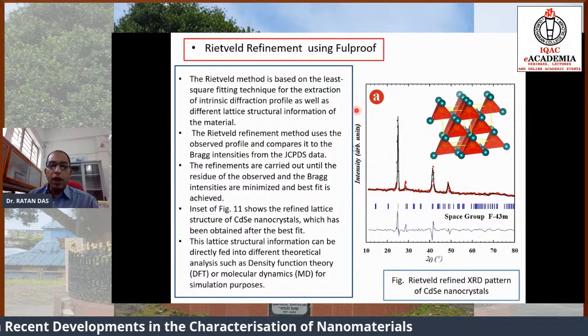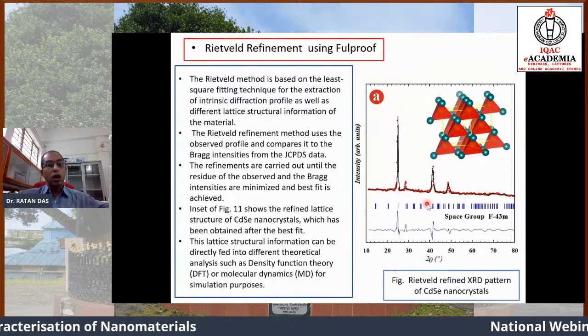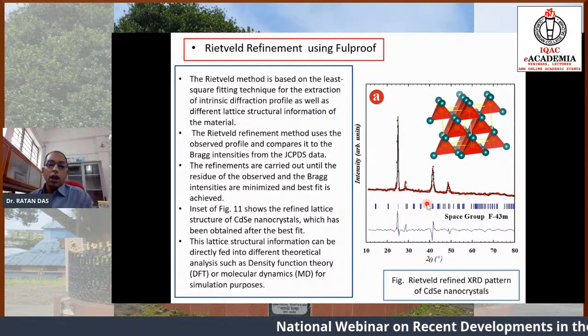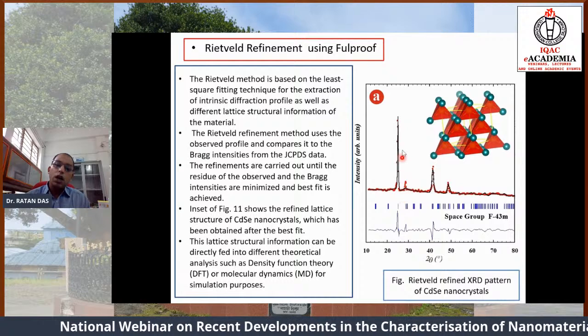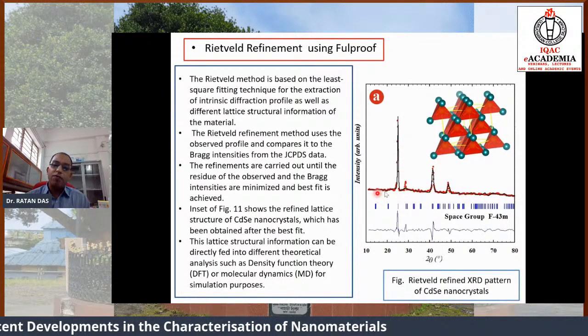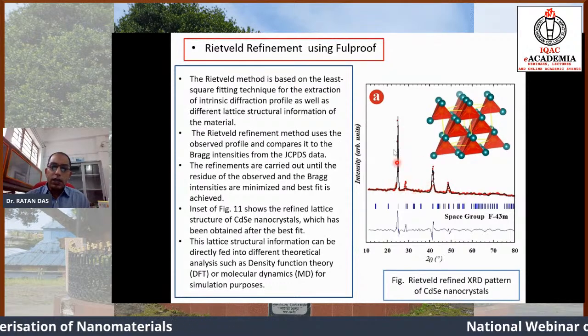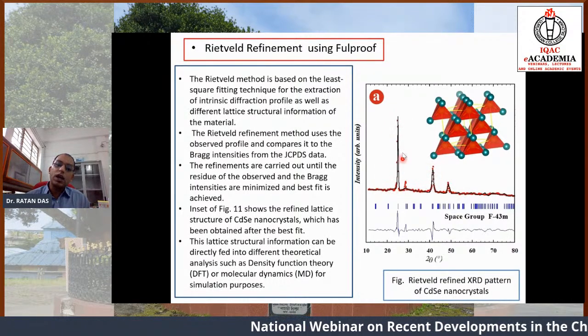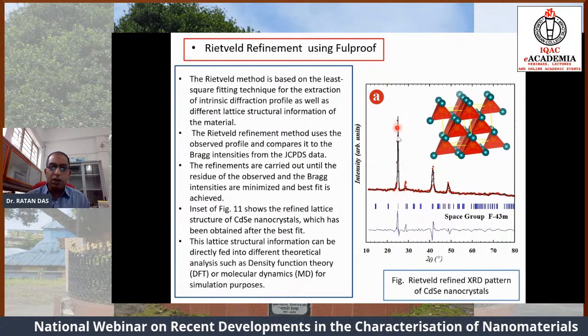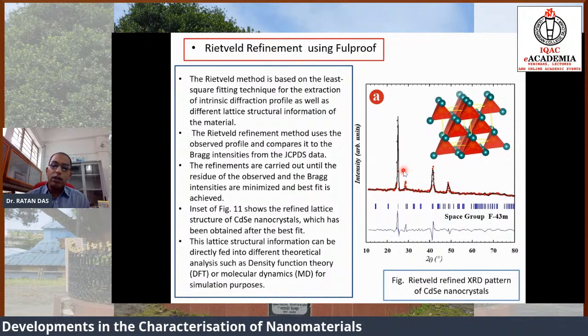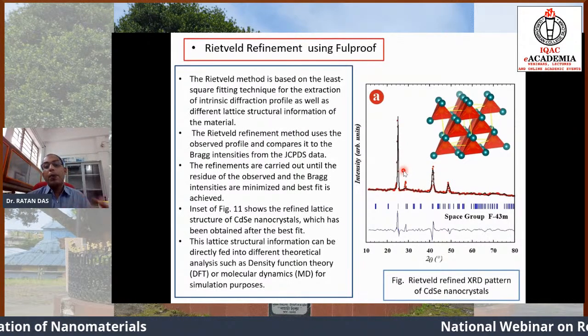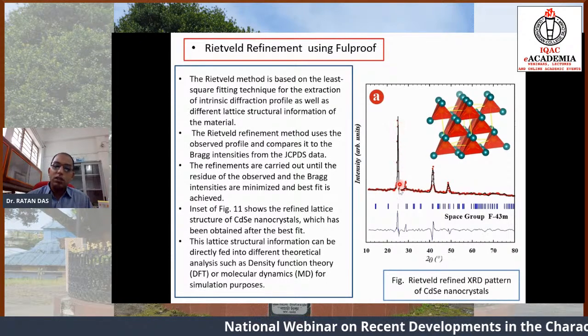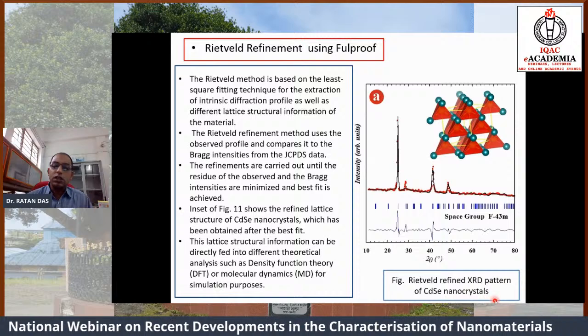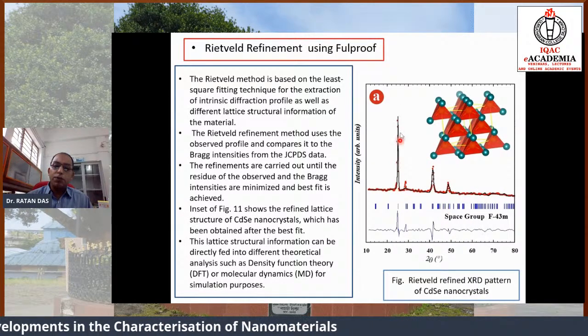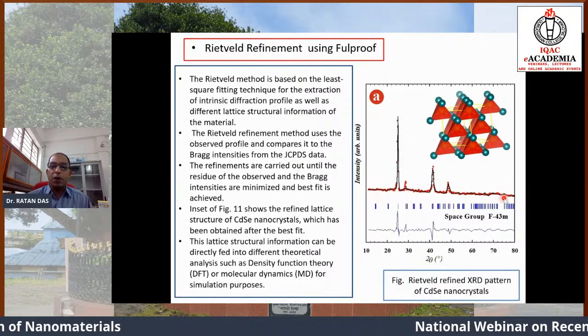Considering a known diffraction pattern or CIF file, we match our obtained diffraction pattern with the Rietveld refined pattern. In the refined pattern, if some peaks deviate from the CIF file pattern, then you can say that your obtained pattern is not matching. Here is the X-ray diffraction pattern of our CdSe nanocrystal that we have prepared, and the diffraction pattern is matching well with the refined pattern. Every peak is matching, and this matching is very much required.